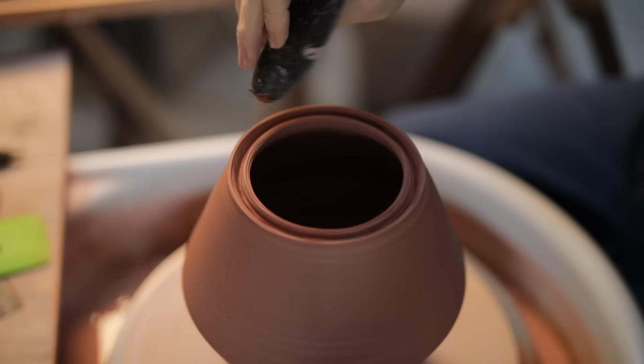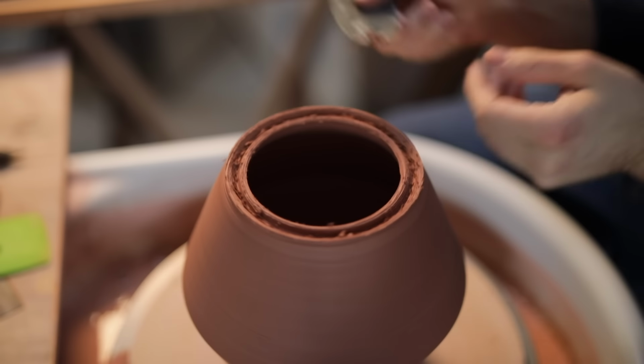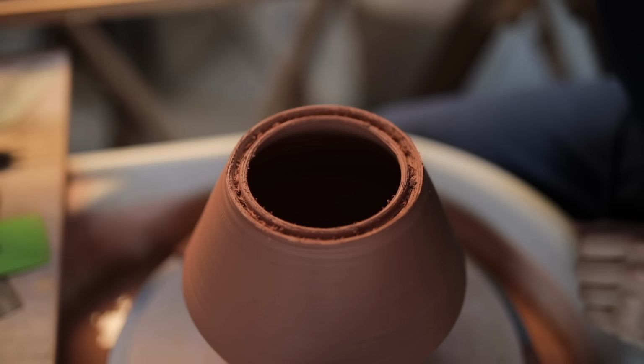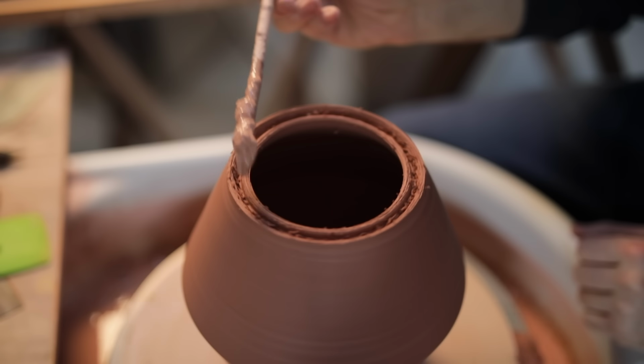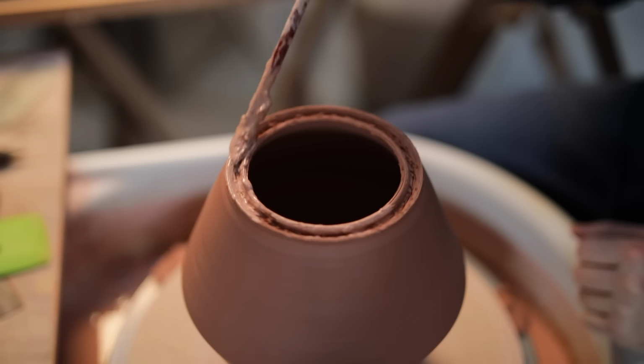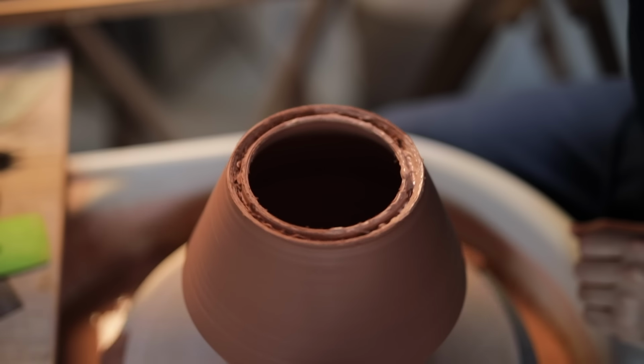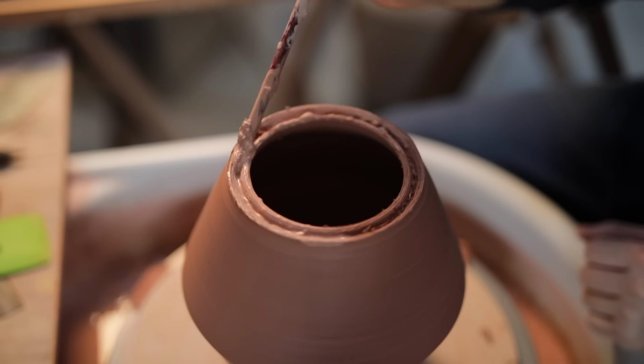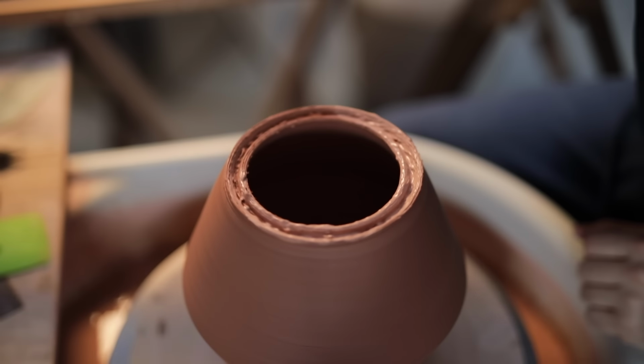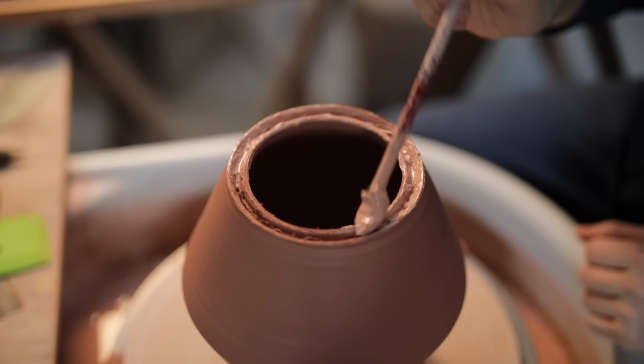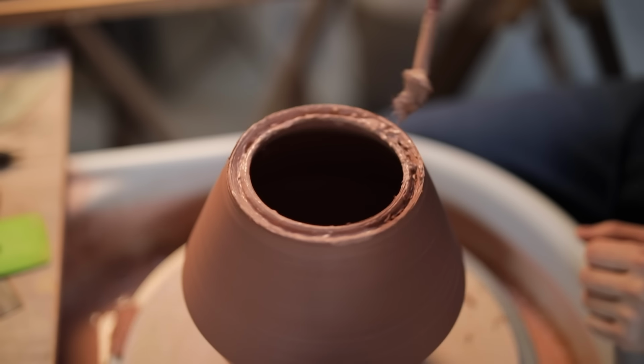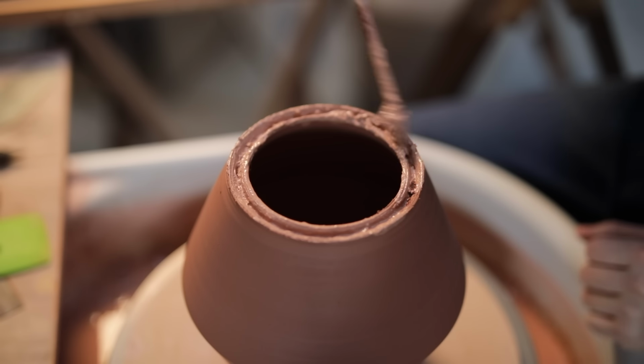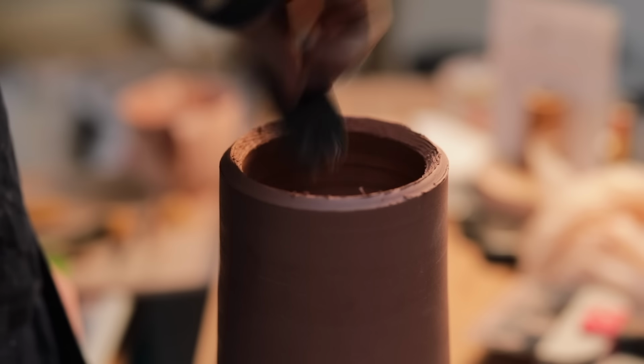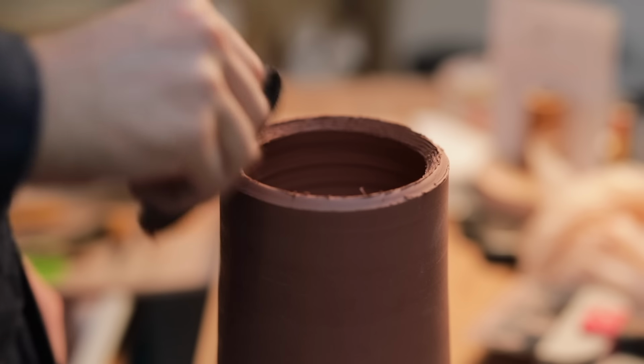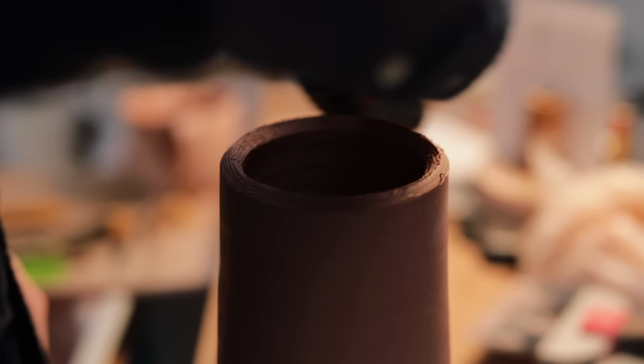Another issue for this batch of pots is that I threw all of the components a bit too thickly, which ultimately meant I had to trim away a lot of clay from the entire vessel, and in 2 cases I trimmed one certain side of the pot far too thin, which meant during the glaze firing this portion crumpled with all the weight of the clay above it. One ended up collapsing and falling against the inside wall of the kiln, but that's something I'll show you towards the end of this video. And another one of the vessels just began to go, the thin clay wall folding, but not quite collapsing.